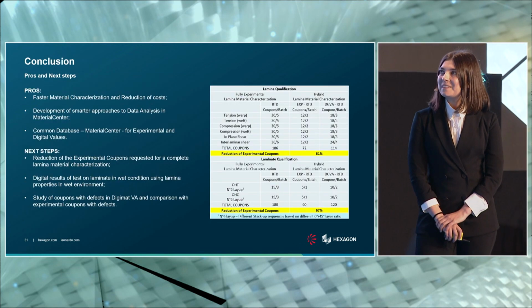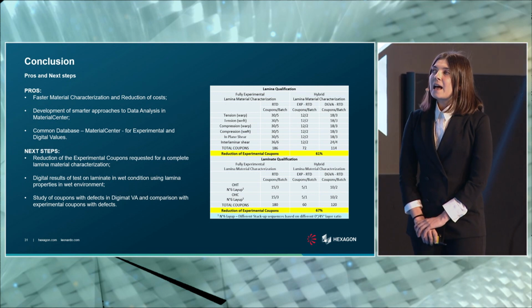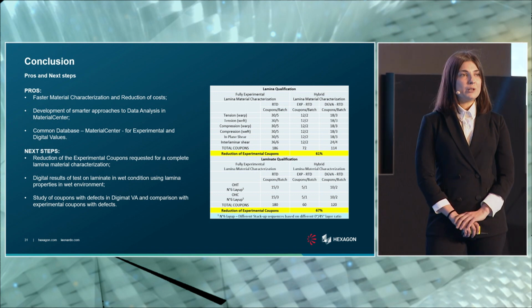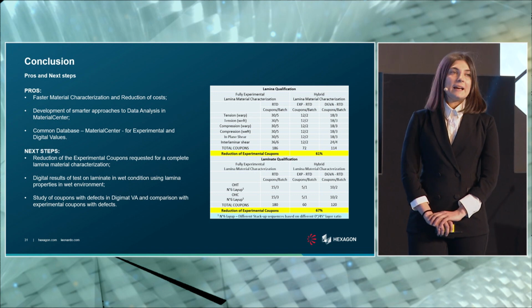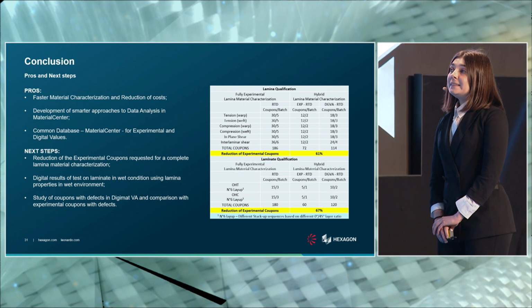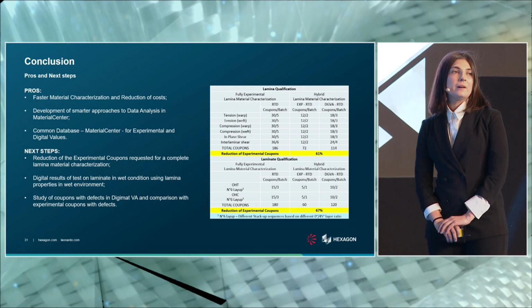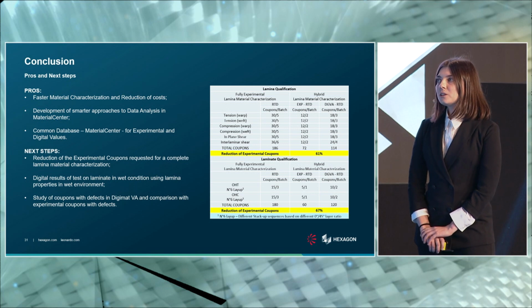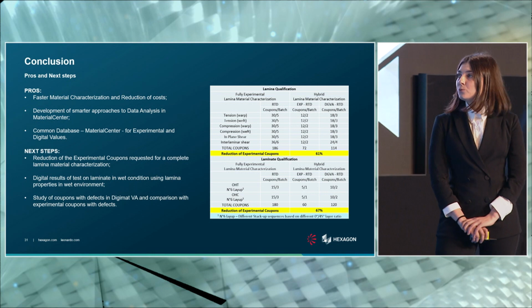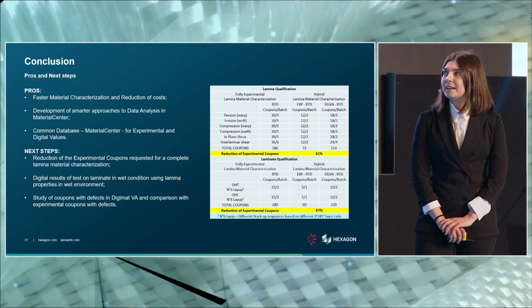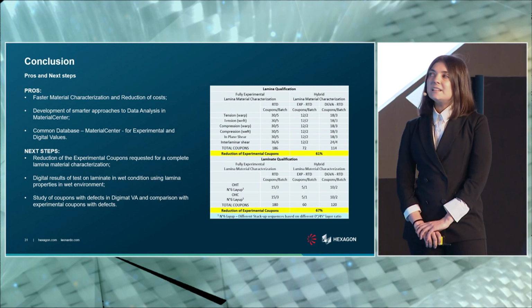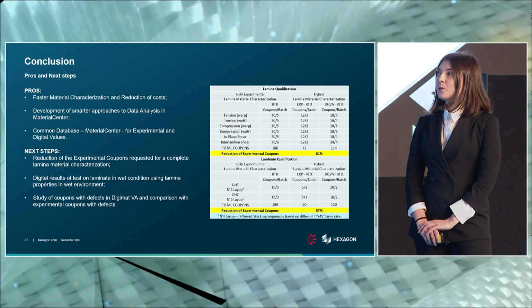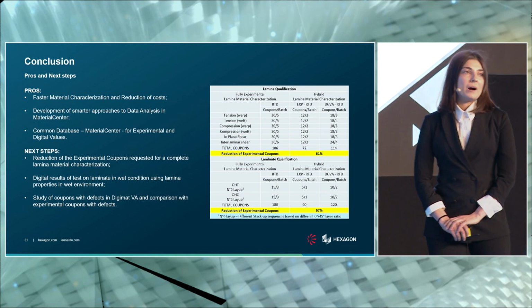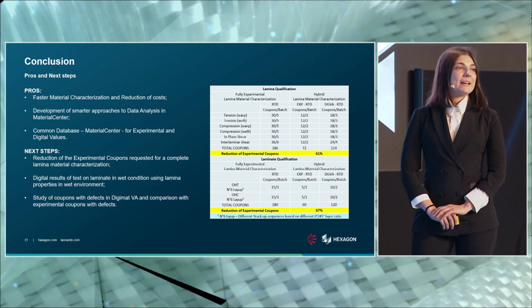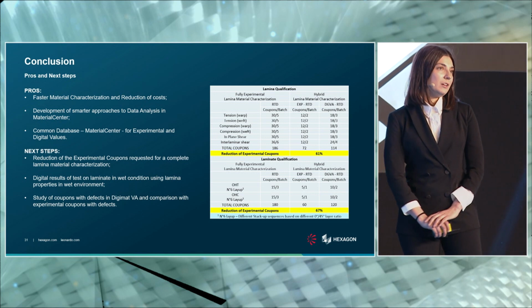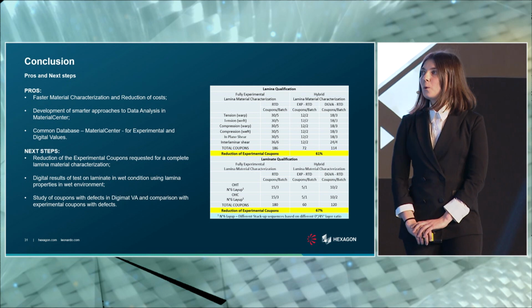Okay. Let's get on with the pros of this project flow. As we have seen in the previous slide, we can reach the same failure mode as the experimental test. Also, we had a very similar result when comparing the experimental batch to the hybrid approach. And we also have all the stress strain curves fitting the experimental ones. For this, the pros are obviously a faster material characterization with a reduction of cost. And in MaterialCenter, we have a smarter approach to data analysis, and we can have a common database of virtual analysis and experimental tests.